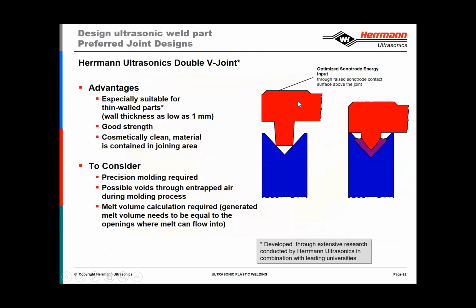So for thin walled parts, the joint design that we recommend is the double V. So here we have 2 points of contact. Again, minimizing the surface area is what's required. But in this case, because of the typical thin walls that we see, the double V joint allows for the flash containment within the melt area, and also has the advantage of working well with thin walled parts.